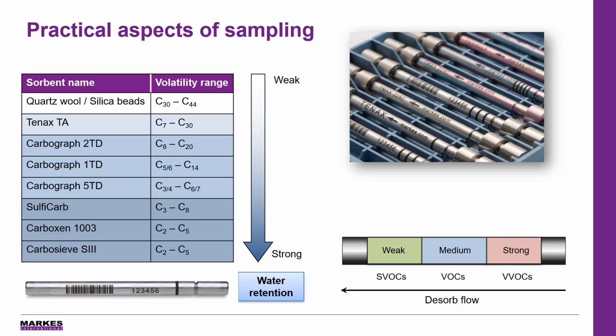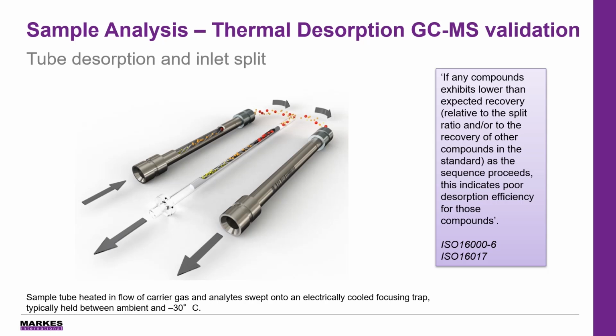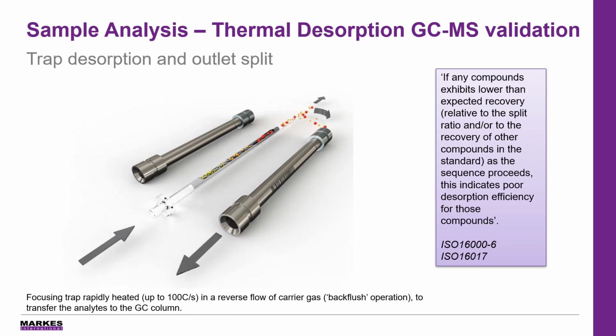Backflush operation is crucial in allowing the use of multiple sorbents to extend our range of volatile organic compounds for TD analysis. When we heat our sample tube in a flow of carrier gas, the analytes are swept off our tube onto our electrically cooled focusing trap, and that's held between ambient and down to -30 degrees Celsius. We do have the option to recollect the inlet split from our original sample tube at this point. Once our sample is on our focusing trap, we rapidly heat up our focusing trap in a reverse flow of carrier gas, our backflush operation, to transfer all these analytes onto our GC column.